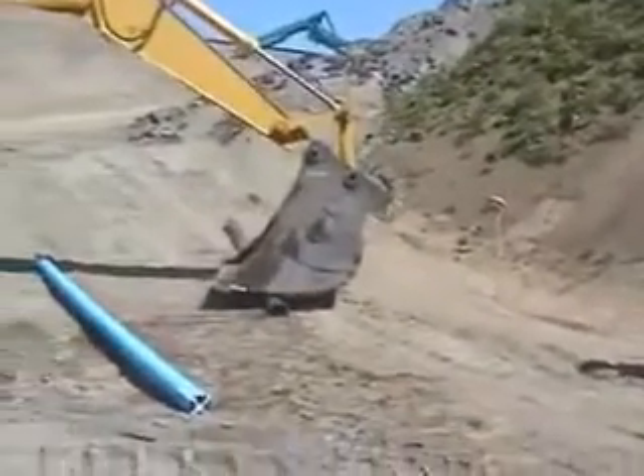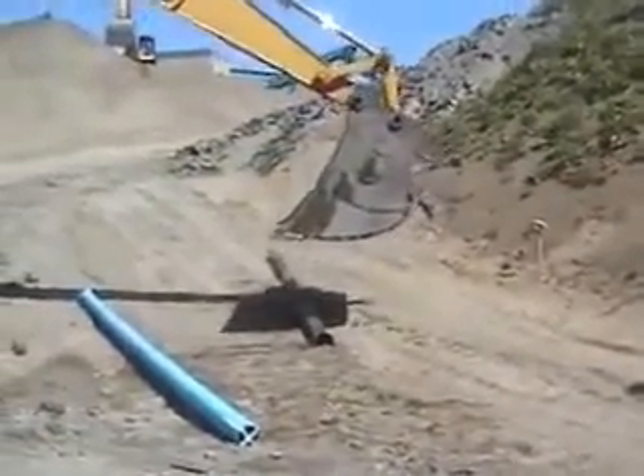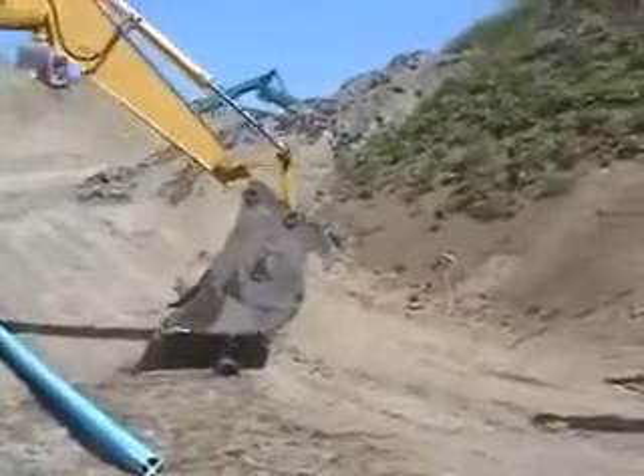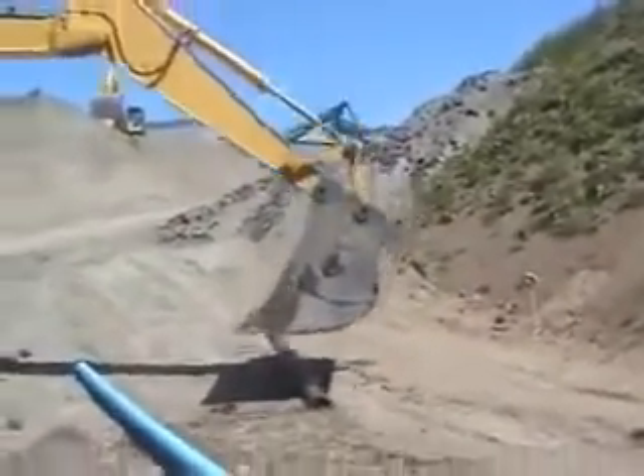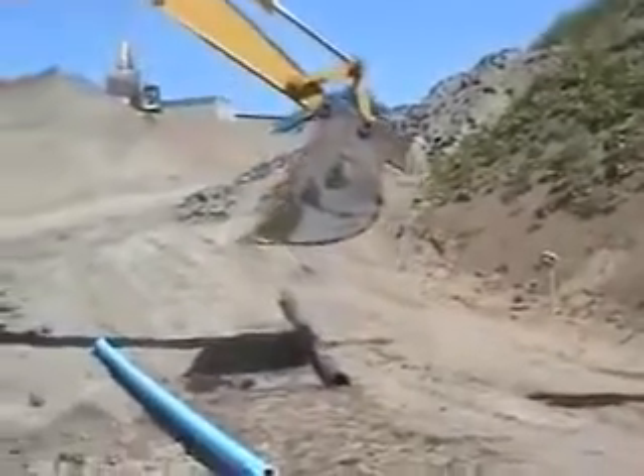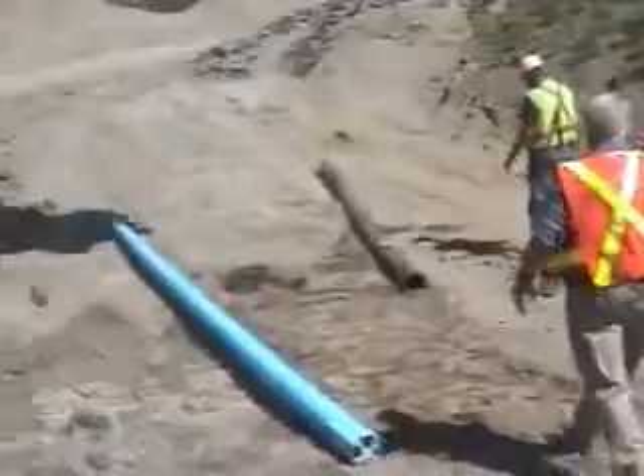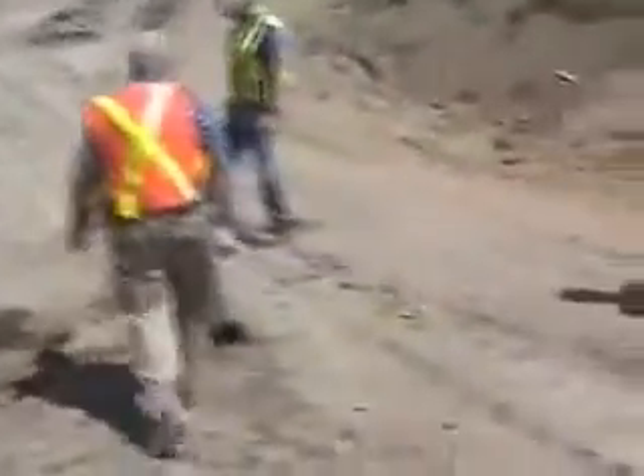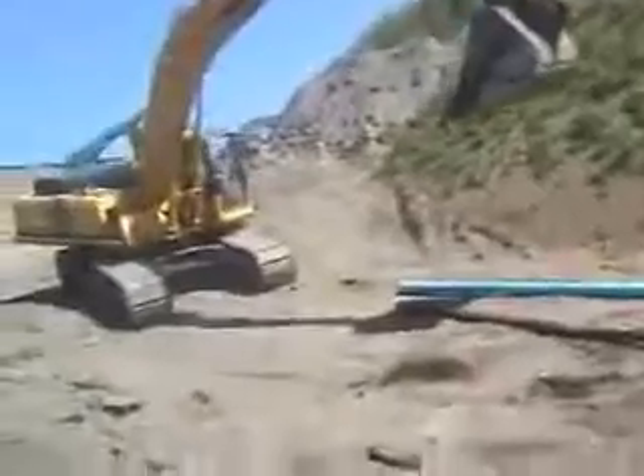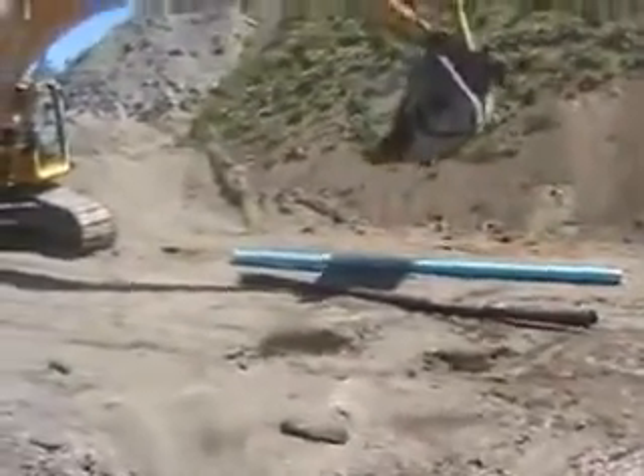The pipes were then impacted with the bucket of a Kobelco 370. The ductile iron became permanently deformed and developed a crack at the point of impact. Additionally, the cement mortar lining broke off the pipe. The same impact was done on Bionax with no detrimental effects on the pipe.